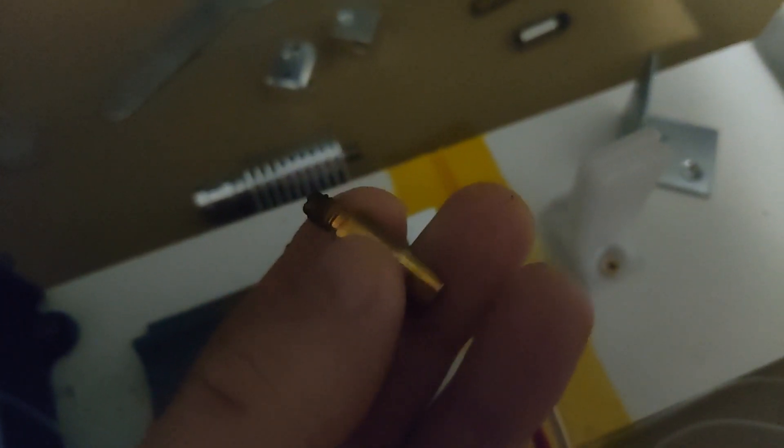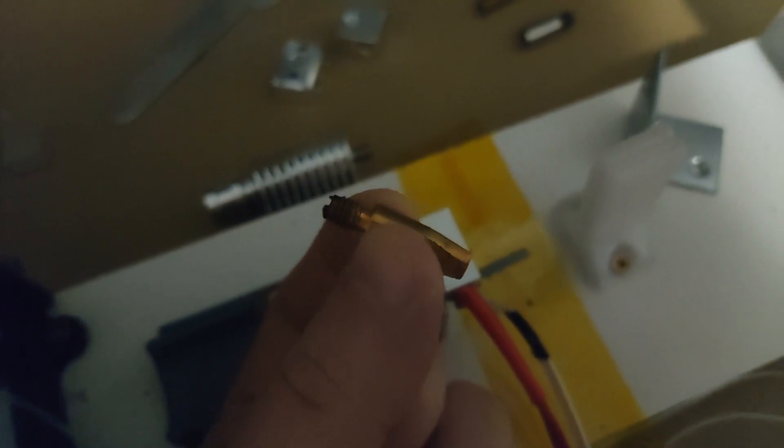Despite being 1.6 I am getting 1.75 millimeter filament out of it. I think it's mostly dependent on width of your plastic bottle strip, not necessarily the nozzle diameter as filament tends to expand a little after exiting the nozzle. It will also be much more precise than a standard nozzle drilled with a hand drill. As you can see I have tested standard brass nozzle and volcano one, but results were average and I had to slow down the spooling process to not snap plastic strips.